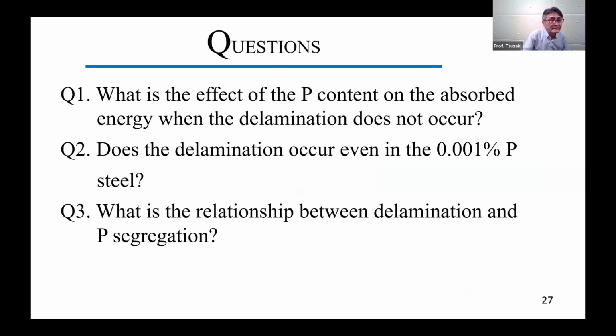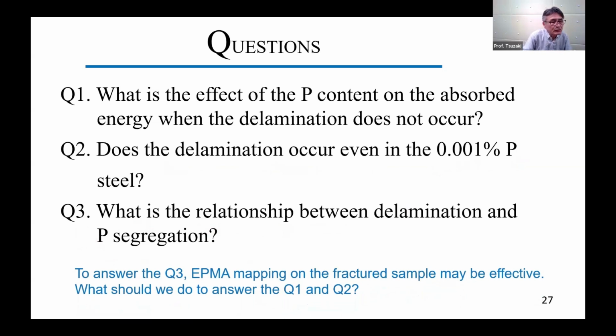Now that you have seen the results so far, you may have these questions. Q1, what is the effect of the P content on the absorbed energy when the delamination doesn't occur? Q2, does the delamination occur even in the 0.001% P steel, high purity steel? And Q3, what is the relationship between delamination and phosphorus segregation? To answer the Q3, EPMA mapping on the fractured sample may be effective. But what should we do to answer the Q1 and Q2?